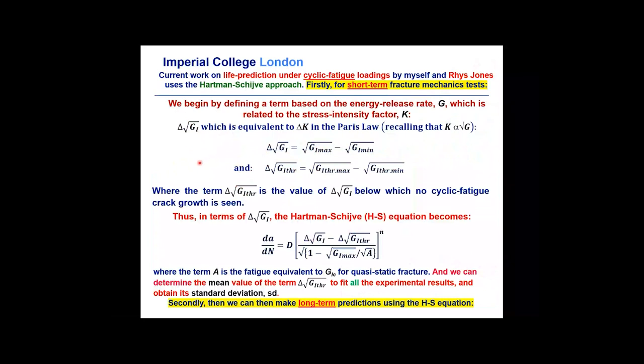We've been looking at life prediction under cyclic fatigue loading, where of course you cycle the joints between a maximum and minimum load. And to skip quickly through the slide, we base it on a fracture mechanics approach. So we have the energy release rate, and we relate to this stress intensity factor, which is involved in the Paris law. Now, the K, the stress intensity factor, is proportional to the square root of the energy release rate, and therefore we define this term delta root G, and that's defined here, where delta root G is given by the maximum energy release rate in our cycle, which corresponds to the maximum load, of course. And here's the minimum energy release rate, which corresponds to the minimum load. So this is max load, min load, max load, min load, as in a fatigue cycle.